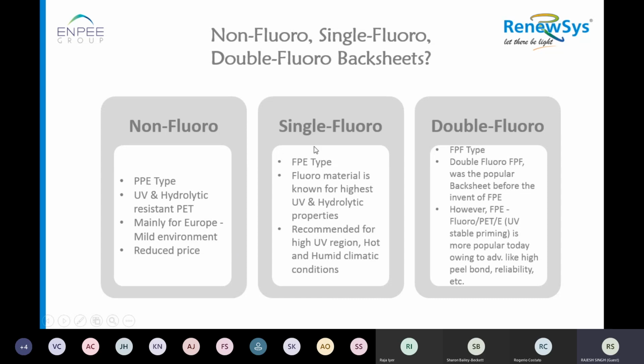Single fluoro back sheet was actually the second stage after double fluoro. Double fluoro was the first back sheet which was introduced maybe 20 years back, in the starting of module technology, where both sides of the back sheet were fluoro, and in fact it was not needed, frankly, because it makes the back sheet structure too expensive. At the same time, it is not too good for getting bonding with the cell, especially from the fluoro side which is towards the cell of the back sheet.